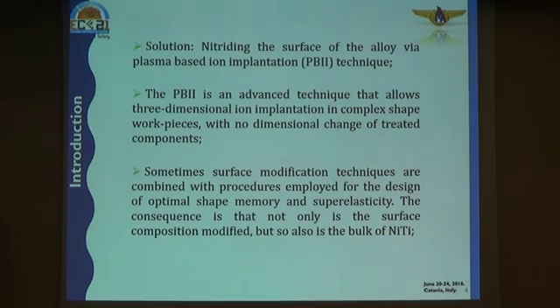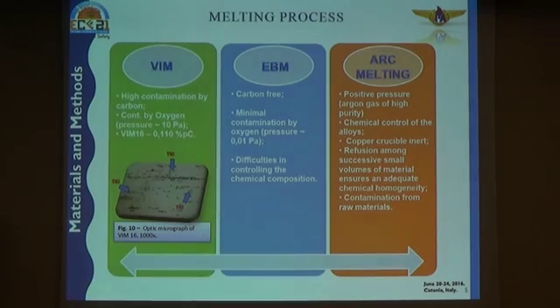The plasma-based ion implantation technique is an advanced technique that allows three-dimensional ion implantation in complex shaped workpieces, with no dimensional changes of the treated components. Sometimes the surface modification techniques are combined with the procedures employed to design an optimal shape memory and superelasticity. The consequence is that not only the surface composition is modified, but also the bulk of the NiTi.